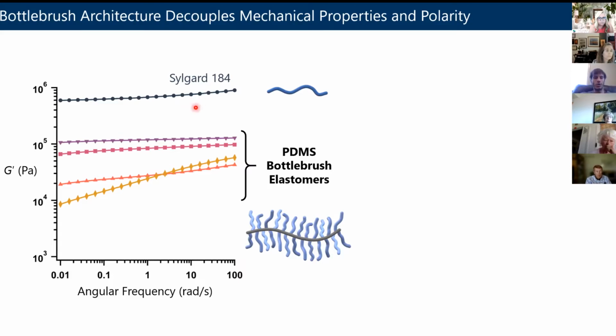And the value of G prime at that horizontal flat line is the stiffness in a rotational kind of deformation. And you can see up here for Sylgard 184, remember, this is your linear polymer elastomer. The stiffness is up around 10 to the 6th pascals. It's up around 1 megapascal. And I want you to remember that number, because that's a pretty good approximation for as low as you can go with a traditional material. The stiffness is going to plateau and flatten out about 10 to the 6 pascals, or a megapascal.